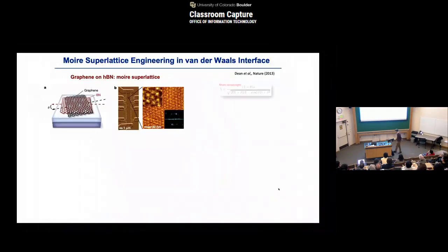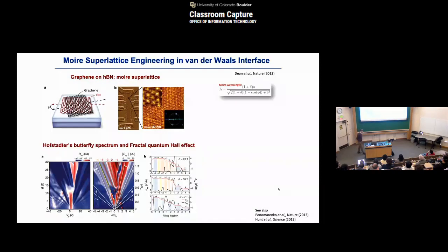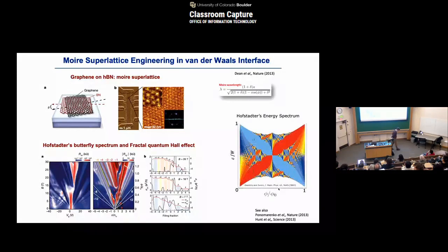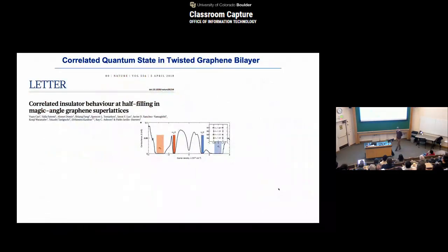In fact, around 10 years ago, putting graphene onto boron nitride and similar systems, people started to see that moiré structures appear in these van der Waals structures, and applying a magnetic field, for example, you start to see the so-called fractalized spectrum, which physicists often call the Hofstadter's butterfly problem. But perhaps the most exciting development happened almost exactly 5 years ago.